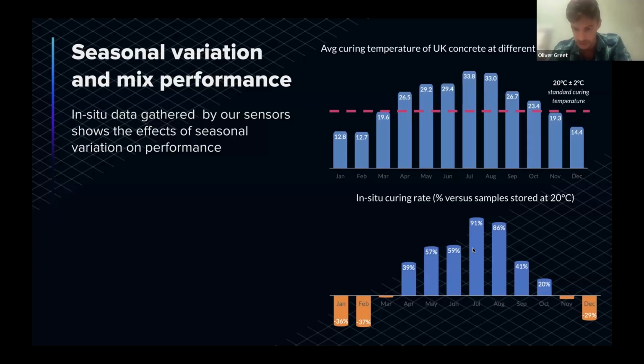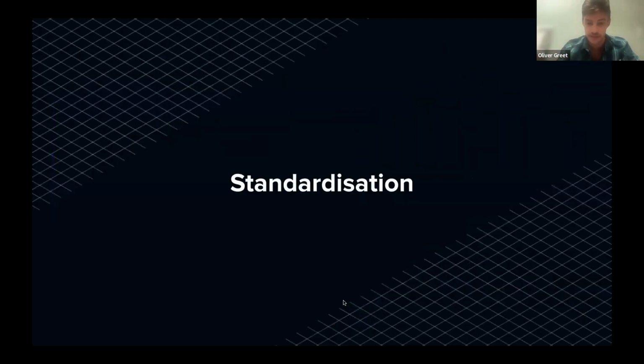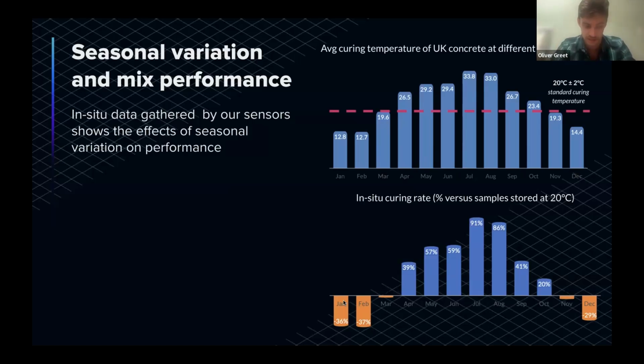So this really highlights why contractors in particular see a merit in using sensors to track strength gain in particularly time-sensitive elements. It can be a question of accelerating their productivity on site, where they want to take account of the fact that the in-situ concrete is actually curing much faster than traditional tests might suggest. But there's also a safety aspect as we go into winter, where we're looking at applications like post-tensioning slabs. If they operate based on the results from a cube stored in standard conditions, they'll get artificially elevated strengths. As a result, that might lead to safety-critical incidents like the breaking out of tendons or anchors.